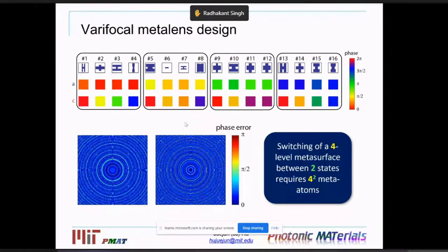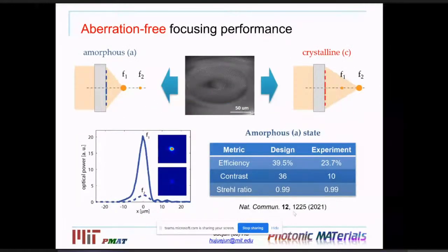Now, in the case of a reconfigurable lens, it gets a bit more tricky, because you have to ensure high efficiency in both states. At the same time, you also have to minimize the phase error in both states. So what we did is develop a figure of merit that allows us to account for both phase error and amplitude in both optical states, so that we can do a quantitative assessment of the different designs and pick out the best ones. You can refer to the paper here. We give a more detailed account of the figure of merit and how to select all the meta atoms.